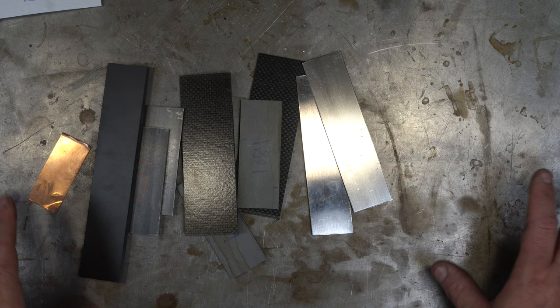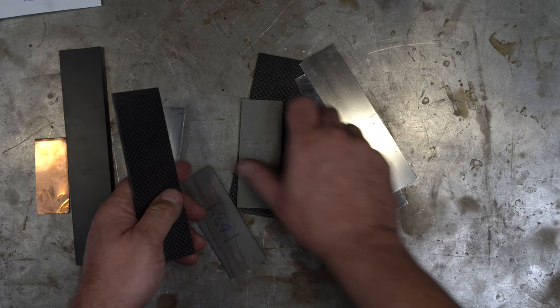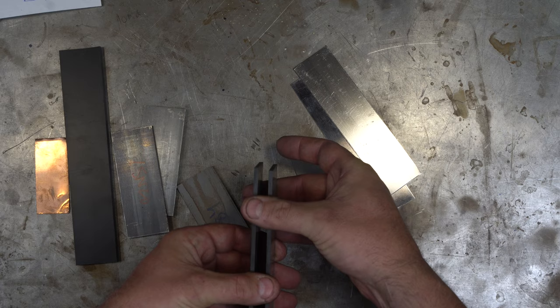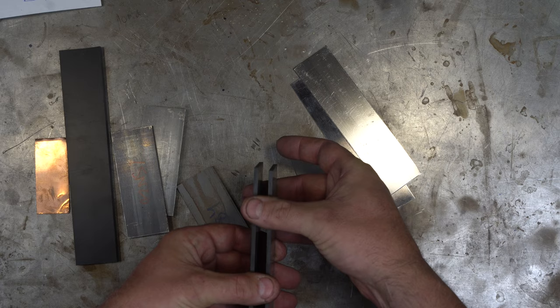So that was a lot of math for some people. So let's do this in shapes and sizes. If you were to do the eighth inch, like I was saying before, so let's say I'm going to use this carbon fiber. It's eighth inch. Let's say, pretend this is high carbon steel or whatever, whatever my cladding is, and I'm going to put eighth inch. So there is my core. I'll do this so you can see it. So if this is my billet, then I'm only going to take this down to three sixteenths. And then I can grind off the sides. If I want it thinner, I'll just grind off the sides so that I don't make the core too thin. What you don't want to do is forge this down to one eighth. This core is going to be way too thin at that point.